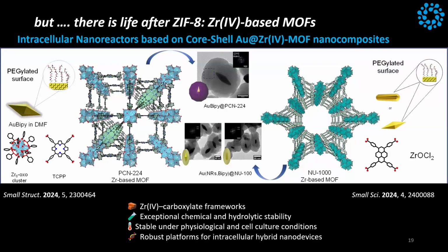And then he has developed different methods, either by preparing the zirconium cluster beforehand, trying to minimize very fast reactions, not 2 days, but half an hour, and so on. He has been able to grow this MOF, this porphyrinic MOF, on top of any nanoparticle. And then he has been able to grow it on rods, cubes, magnetic nanoparticles, quantum dots, anything.